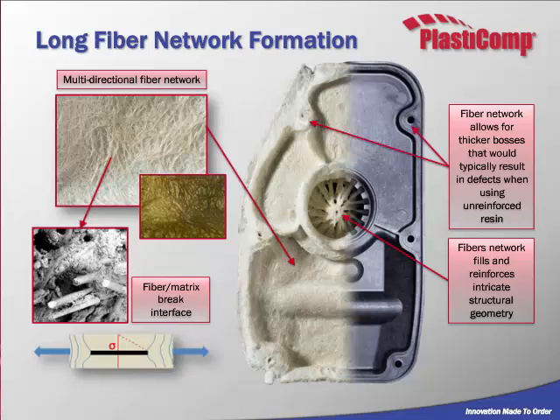Right under that, you see an image of a fiber break section. This is where you can start seeing a residue on those fibers. And that residue is a good thing. It means that it actually bonded to the resin matrix around it, which added resistance to the break. It had to pull out all of that extra bonded area from the other side. The image below that is a stress diagram of how each fiber is gripping the matrix around it, just to give you an idea that there is a surface bonding relationship to that matrix.